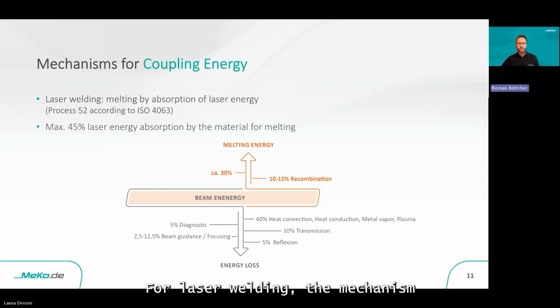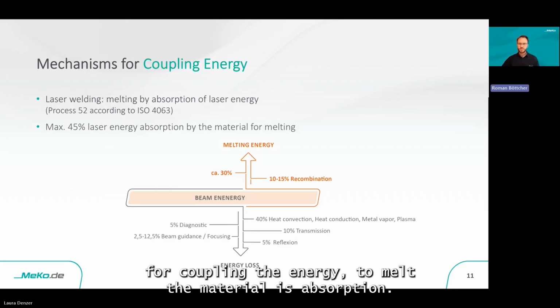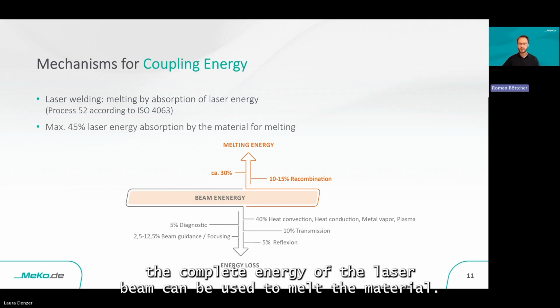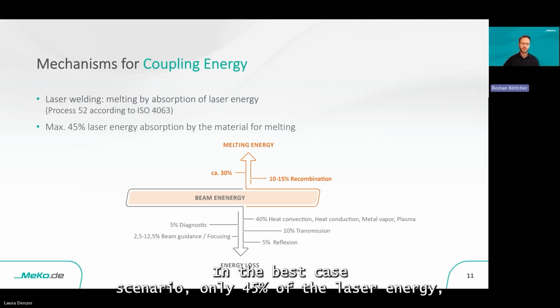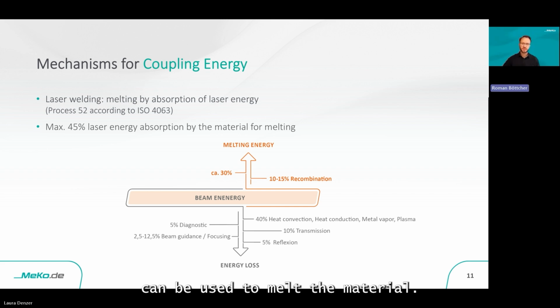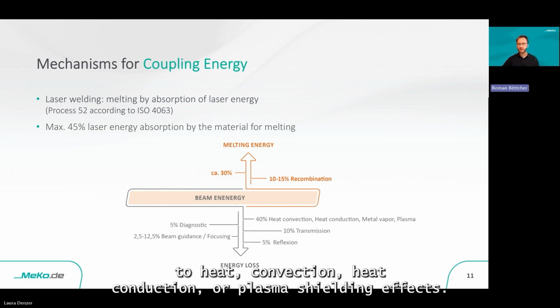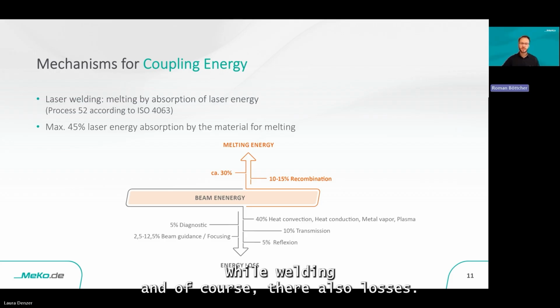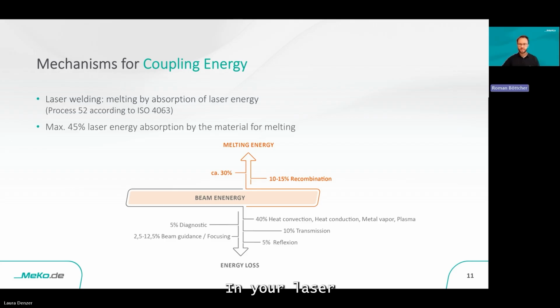for laser welding, the mechanism for coupling the energy to melt the material is absorption, but not the complete energy of the laser beam can be used to melt the material. In the best case scenario, only 45% of the laser energy can be used to melt the material, and there are some losses due to heat conduction, or plasma shielding effects while welding. And of course, there are also losses in your laser guidance system from the laser source to your workpiece.